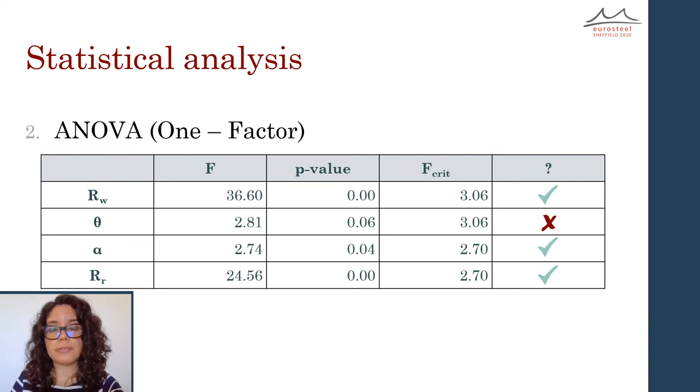Because of this, a one factor analysis of variance was conducted. According to this statistical analysis, the variation in the neck angle does not affect the variability of the results.